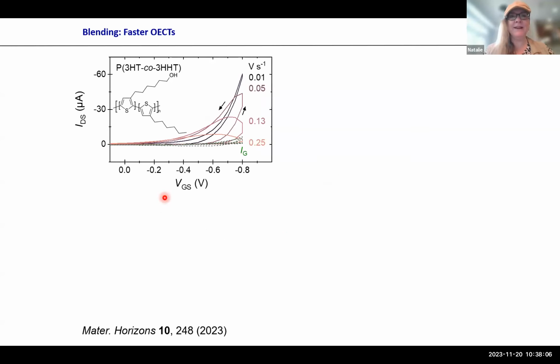Now here you see similar characteristics as for normal transistors. So this is an organic electrochemical transistor where we plot the gate bias. Remember, in the normal transistor, the gate helped us to create charges at an interface. Here, it's simply the gate is an electrolyte and it drags the ions into the system. And therefore, the higher the gate bias, here negative, you get actually a current. You immediately see, though, a problem.